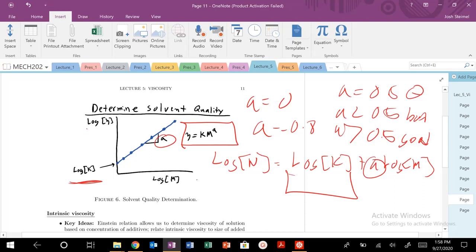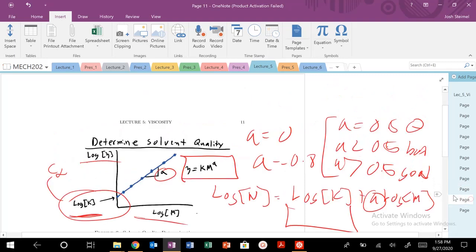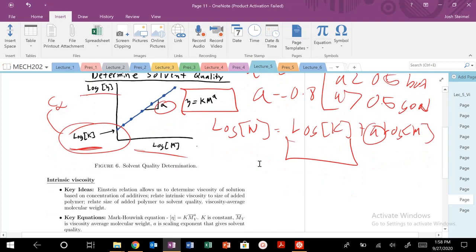From this one single curve — how intrinsic viscosity scales as a function of molecular weight — we can gain all the information we need. From that slope we get information about solvent quality, and from the y-intercept we gain information about C-infinity and these other constants. This is the critical graph from our discussion of intrinsic viscosity. From solvent quality, we can tell if it's a good solvent, the chi parameter is probably low because the components like to mix; if it's a bad solvent they don't like to mix, and we can gain information about chi and mixing.